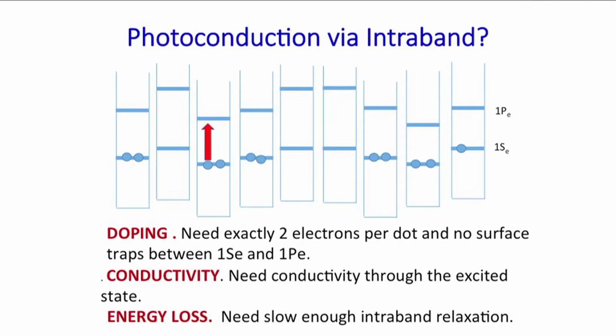So this is kind of the picture. We have disorder. There's always disorder in the systems. We never have perfect dots, and they're never in perfect position. So we're trying to see a photoconduction response after excitation of this electron here, and hope that this electron somehow is going to transport through that layer of states. But that's not obvious. First, if we don't have an exact doping, what is going to happen? The electron will go here, and then most likely it will come down here, and it's done, over, finished.